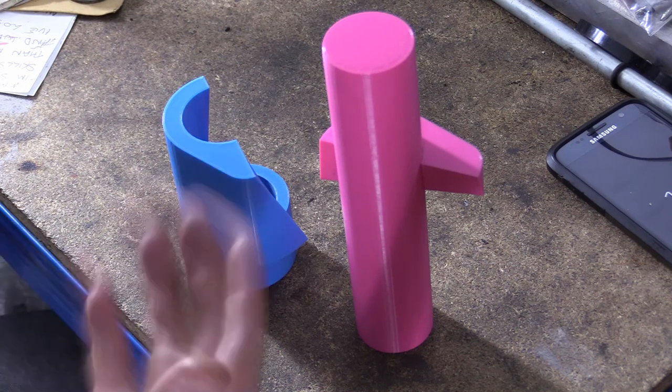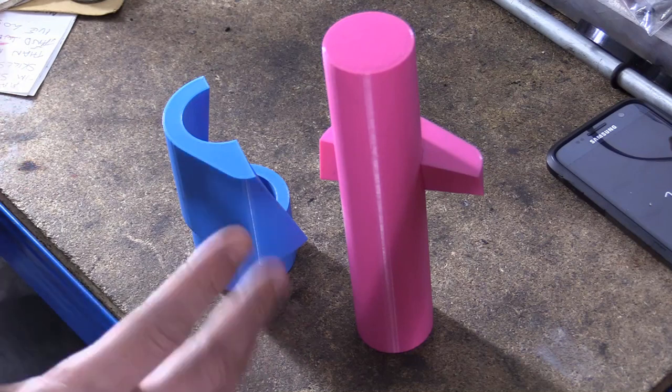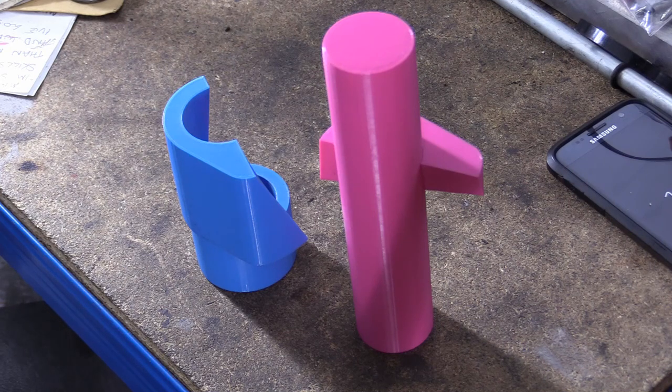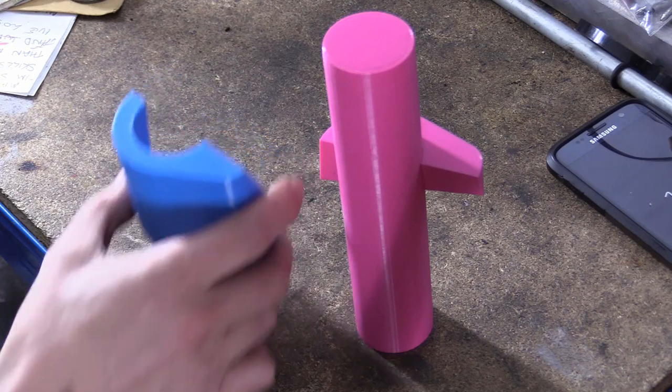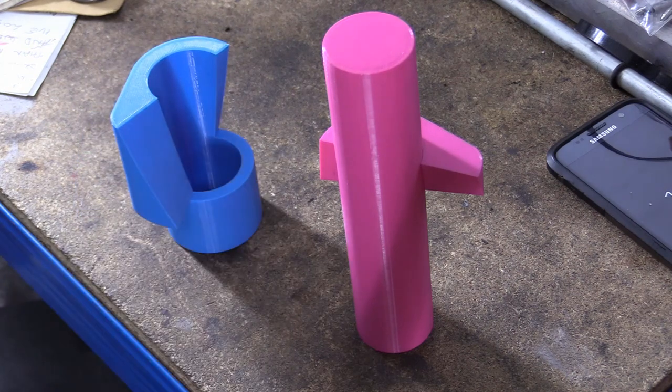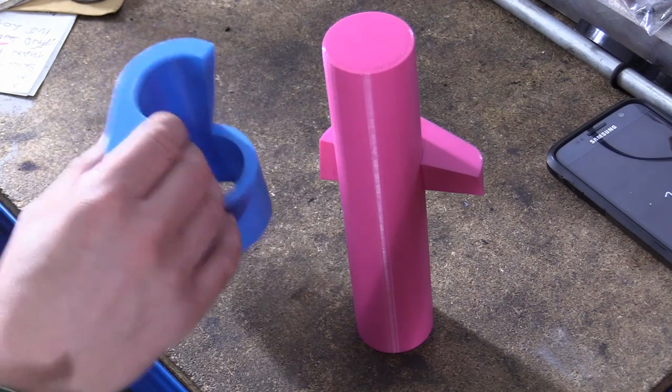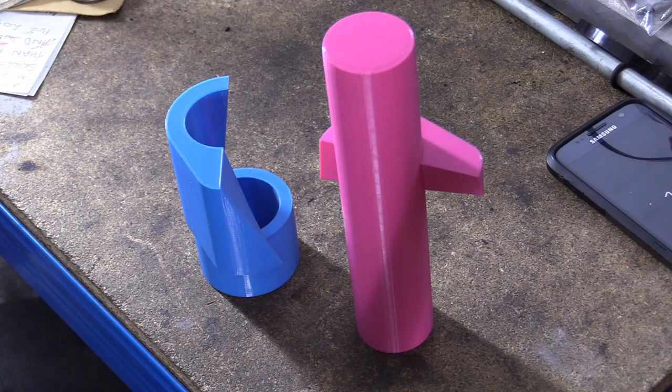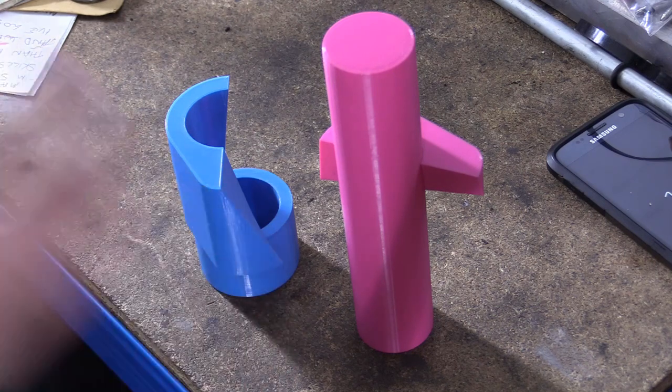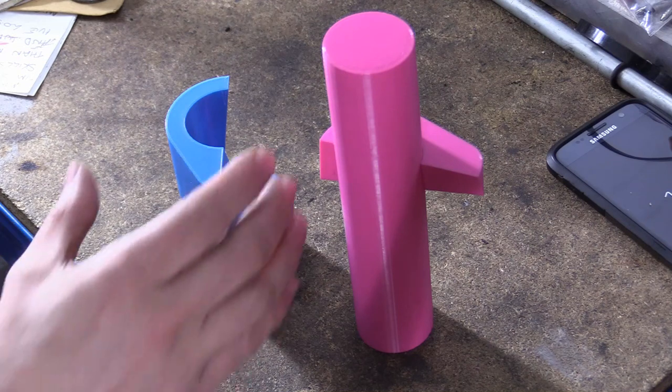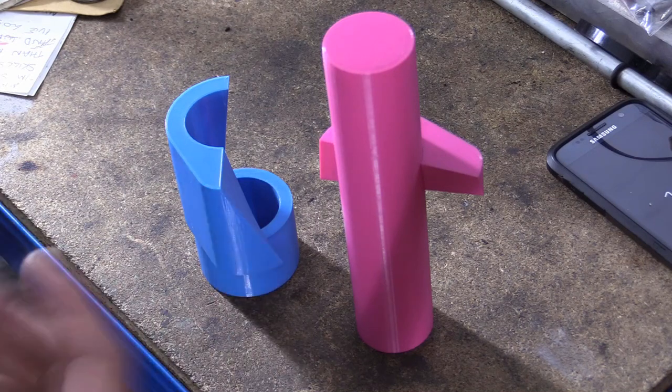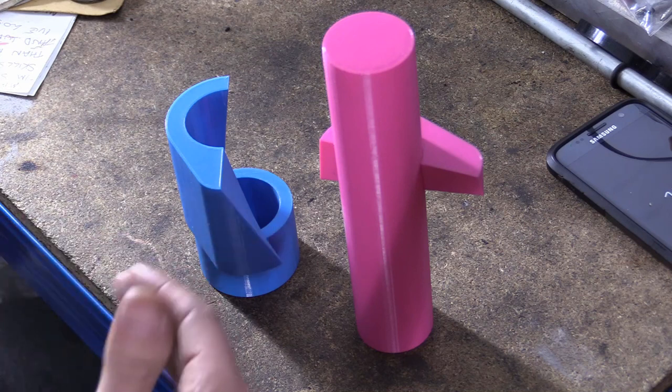Why do you have to do it this way? Why do you have to harden it and then machine the profile onto it? Grinding is a machining process. Why do you have to do that? If you cast this, machine this to the perfect size, CNC or not, then went and basically heated this up and then quenched it, you are not going to end up with the same size material. It basically expands and contracts and goes all over the place. Now it's hard, it's hard and out of spec. It's out of the tolerances. This is why hardening swords and blades, you harden it and then you grind it afterwards so you get your finished dimension.